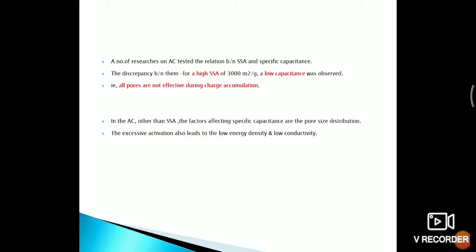A number of researchers tested the relationship between specific surface area and specific capacitance in activated carbon, but they observed a discrepancy between them. That is, at a high specific surface area of 3000 meters square per gram, a low capacitance was observed. It shows that not all the pores are effective during charge accumulation. So, other than specific surface area, another factor affecting the specific capacitance of carbon materials is pore size distribution. Besides that, excessive activation also leads to low energy density and low conductivity.